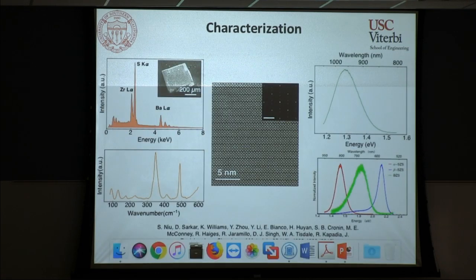So the first one, we were able to get the barium 3 zirconium 2 sulfur 7 in single crystal form, several hundred microns in lateral dimensions and also in thickness. And so we did chemical characterization analysis. We were able to show that they have the right composition. And when we did STEM measurements, scanning transmission electron microscopy, we were able to clearly see these two perovskite blocks sandwiched between the rock salt layer.